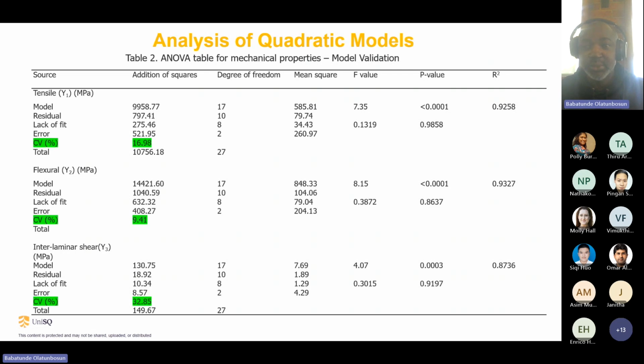You could see the R-squared values are between 0.9, 0.93, 0.92, 0.87. This means that when you have a value very close to 1, it shows how reliably your model can predict the parameters in question. Also you can see the F value and the P value, which is less than 0.1. These are indications of the validity of the model.